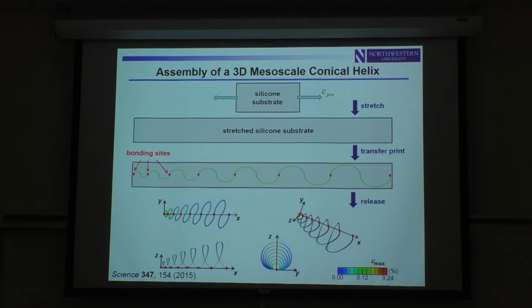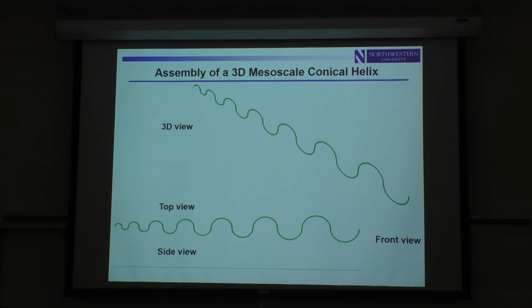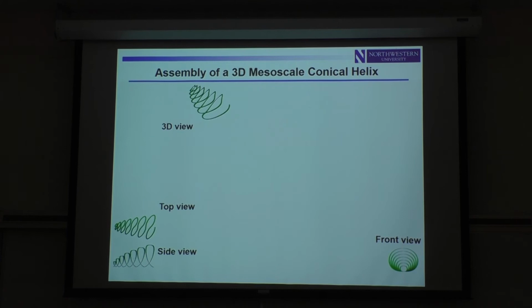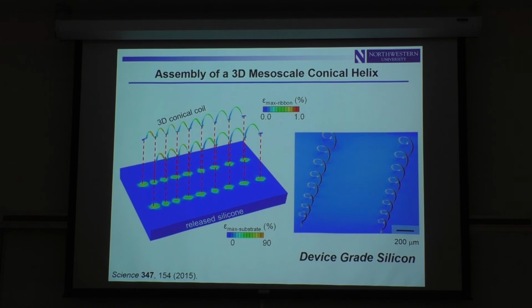slide. So this is a finite element modeling analysis of that process from several different viewing angles. So this is a 3D view, so 2D to 3D. So it grows up out of the surface as you relax the pre-strain in the substrate, and it accomplishes that kind of 3D architecture. Just a very simple example to convey the ideas, and I'll show you much more complex systems in a second. So we do full 3D finite element modeling of the mechanics.